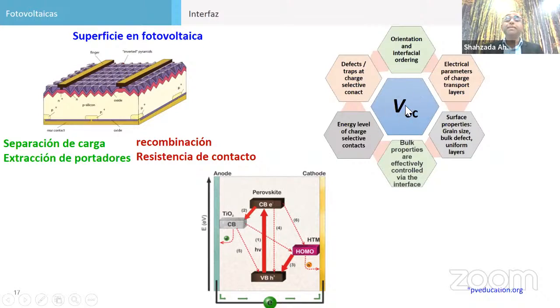So to improve the VOC, basically, by doing so, we will increase the VOC. VOC is the open circuit voltage of the devices. And for this, we have to design energy levels. We have to design the energy level of the charge selective contact. We have to define effective control of the interface, the orientation of the layering of the molecules, how they orient, whether in parallel or perpendicular directions. If we do passivation, we have to address defects. We have to put traps which can check the charge selective contacts. And electrical parameters of charge transfer, high mobility and conductivity, and surface properties, the grain size and defects of the perovskite. These are all things for today.